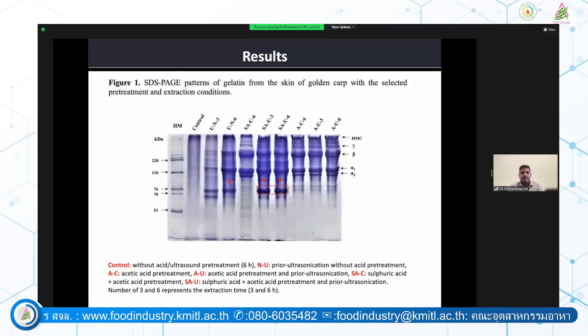which can be a good indicator for application in the food industry. So this is the protein pattern of the extracted gelatin, and we can see here that without acid treatment, there is no band pattern of gelatin. The signature band pattern of gelatin has high molecular weight chains: the gamma chain with higher molecular weight, the beta chain, and two alpha chains, alpha 1 and alpha 2. So this is the signature pattern of gelatin. As we can see, this signature pattern with the acetic acid extracted sample was very perfect.